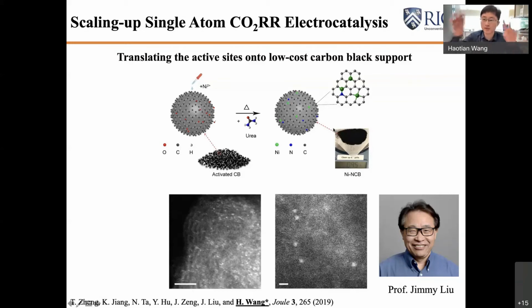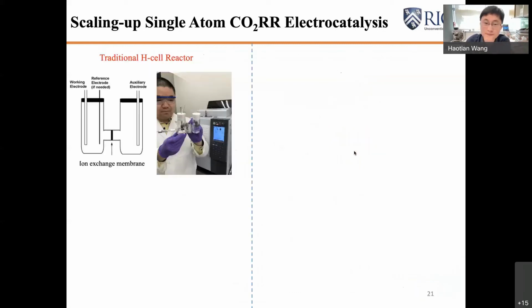So we did the same thing. We dig holes in the carbon black. We disperse trace amounts of nickel atoms and do the annealing. As we can see from this carbon black substrate, we still get isolated nickel single atoms without a problem. And now we can get gram scales from one batch of synthesis, different from the previous graphene substrate. We only get milligram scales of catalyst.